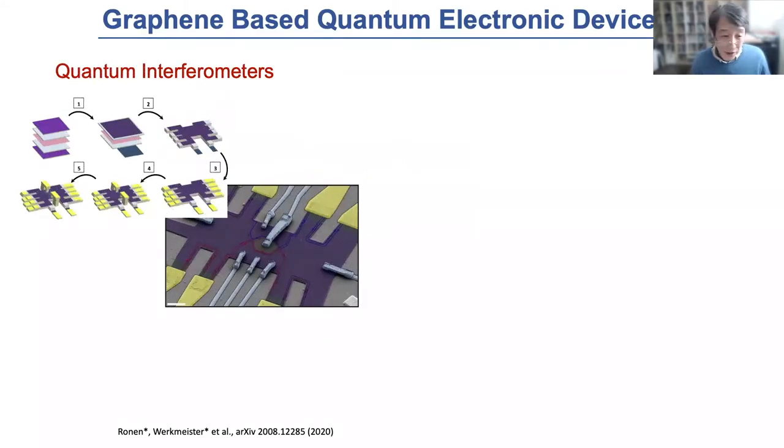And that immediately allows us to build many interesting quantum devices I just mentioned. For example, here's one device example. We carefully encapsulate the graphene in between boron nitride and put top and bottom graphite gates. You can see that within the stack, everything is van der Waals stacks, like in this TEM image of the semiconductor heterostructures. If you cut it out, you will see atomic-scale heterostructures where everything is controlled and everything is van der Waals materials. And then you can make careful contacts and top and bottom gates and rather complicated gate structures.